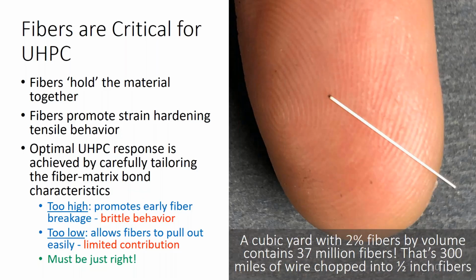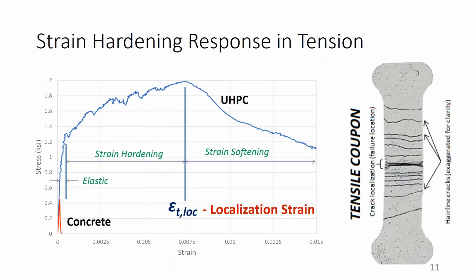So on the right there, I have an interesting statistic. A cubic yard with 2% by volume fiber, that's how we measure it, by volume, has 37 million individual fibers. If you put them end to end, that's 300 miles of wire chopped into half-inch pieces. So with so much effort, you must have really high expectations. And indeed, you should. So looking at the tensile response, which is one of the key properties of UHPC,